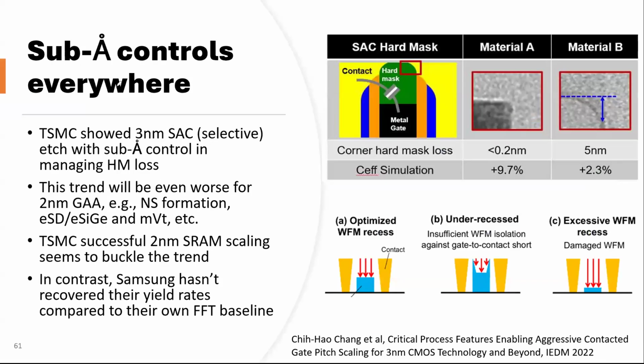And then look at sub-angstrom control everywhere. Look at their 3 nanometer selective etch for the contact, self-aligned contact. This is a self-aligned contact. The alignment of the contact has to be perfectly optimized. Under, over, no good. And what I demand is that the hard mask corner here be 0.2 nanometer, 2 angstrom. In this corner, the mask loss has to be less than 0.2 nanometer. That's just mask loss. What about the other material? So overall it had to be sub-angstrom. That's why I meant sub-angstrom control everywhere.